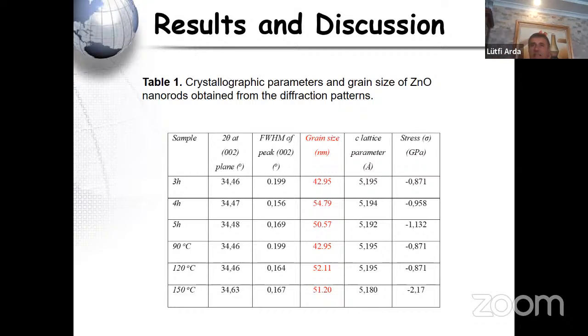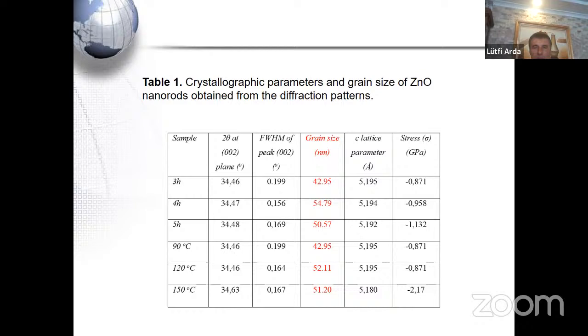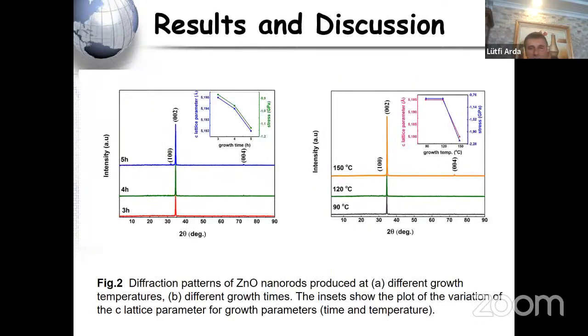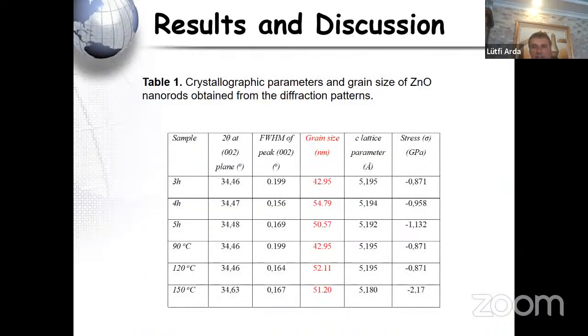And this is the C parameter I plotted above. Let me check here in the inset. Look at the C parameter versus growth time, and the C parameter versus growth temperature. You can see all this. This reduction in the C lattice parameter can be associated with compressive stress, and we also calculated the compressive stress of the samples, which occurs owing to increased temperature and growth time.